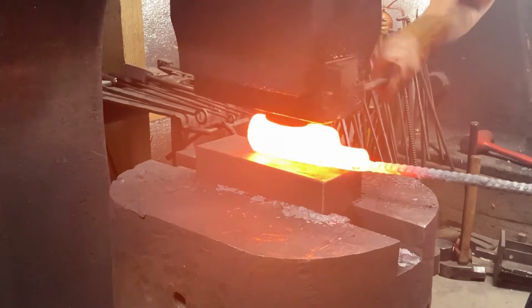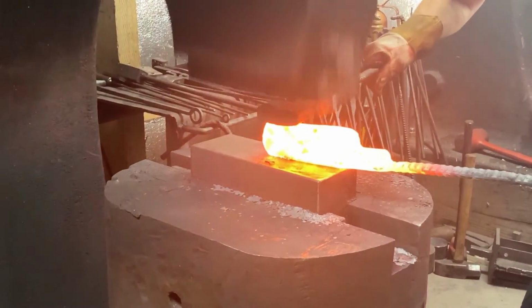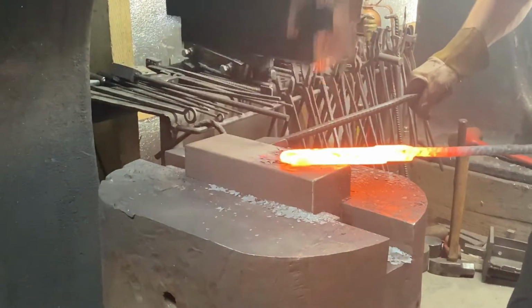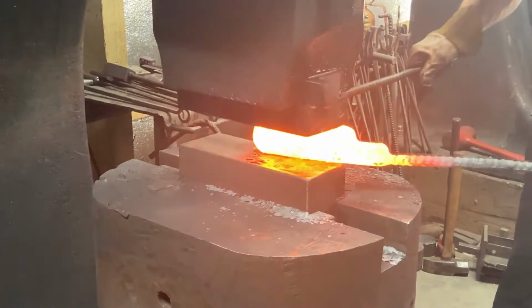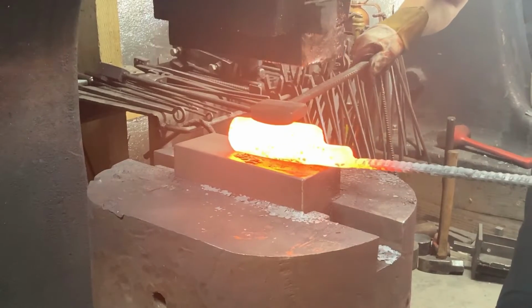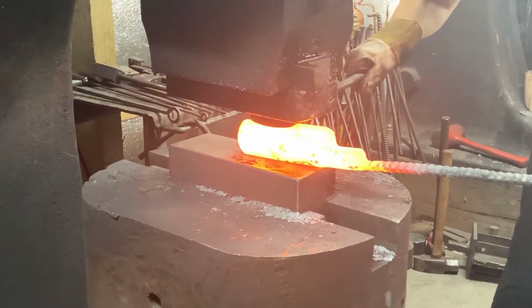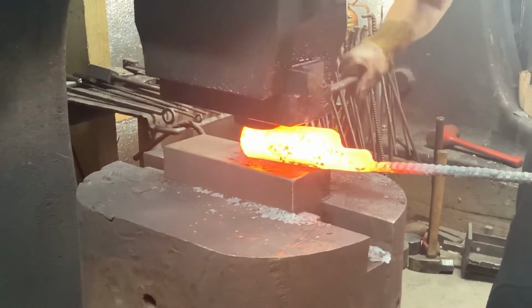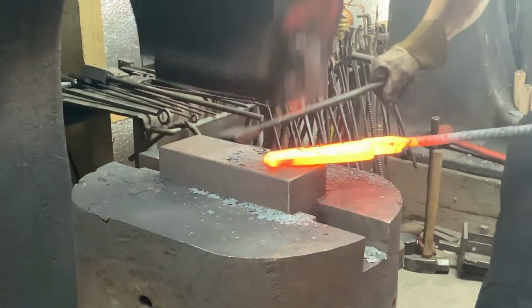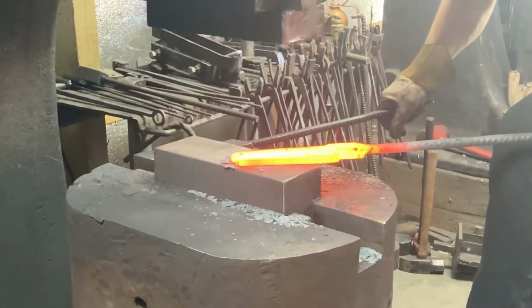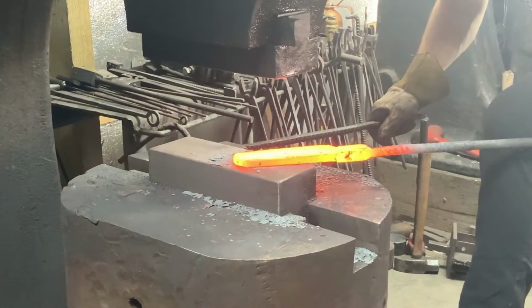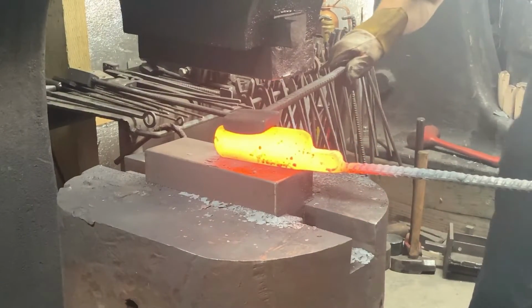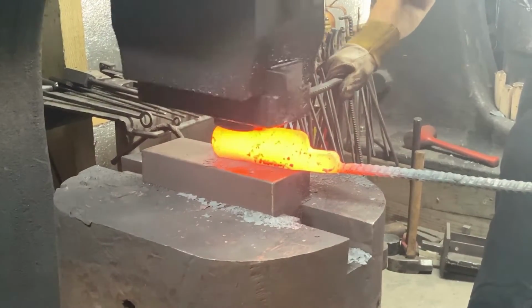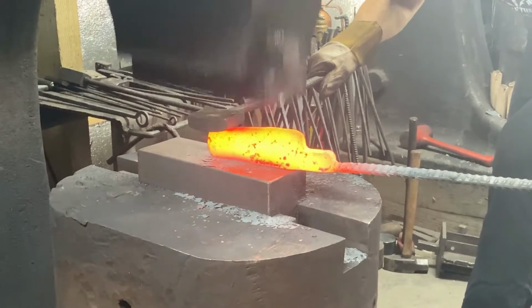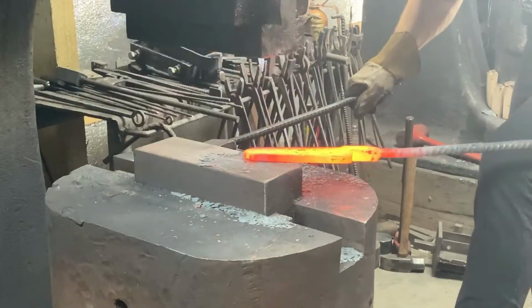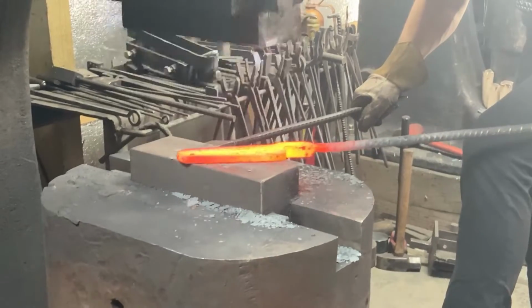Here I'm using a crowned light width drawing tool. It's basically a mellow top fuller, and I'm using that to begin gradually blocking out the taper out to the tip. And you can do this stuff with a hand hammer, of course. The only thing is the billet is still between 3/8 and a 1/2 inch thick here, so it just helps to get the power of the power hammer into it right now.